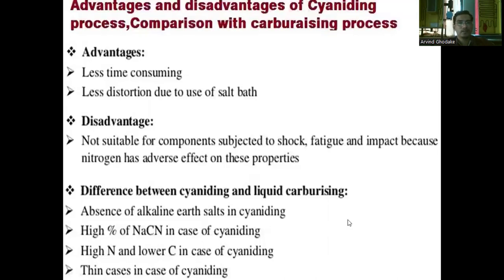Advantages and disadvantages of cyaniding compared to carburizing: the first advantage is it is less time-consuming, and there is less distortion due to the use of a salt bath. The disadvantage is that it is not suitable for components subjected to shock, fatigue, and impact, because nitrogen has an adverse effect on these properties. The differences between cyaniding and liquid carburizing include: absence of alkaline earth salt in cyaniding, high percentage of NaCN in cyaniding, and high nitrogen with lower carbon content in cyaniding.